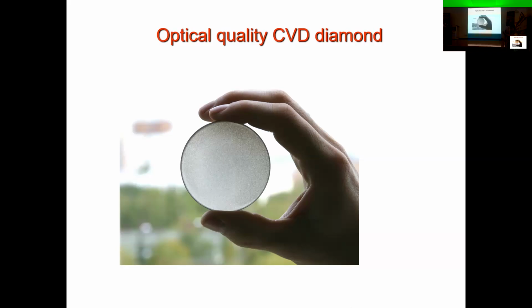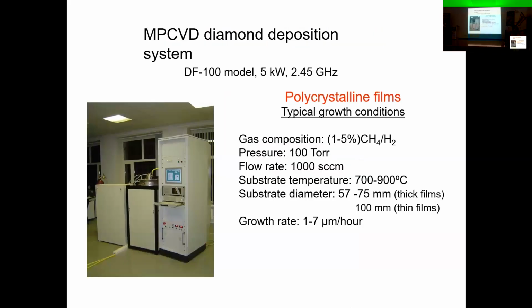It's millimeter thick or 2 millimeters thick. At the Diamond Conference, I have also seen bigger glasses, like 50 centimeters big and 2 millimeters thick. But this is polycrystalline diamond. So it also makes a difference, because monocrystal always has slightly different properties than polycrystalline material. But even so, this polycrystalline diamond has extreme properties and you can apply it for different applications, also biomedical. This is an apparatus for obtaining such material.